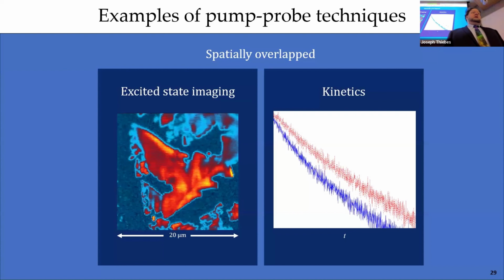And if you do it in spatially overlapped mode, as I mentioned, you can scan over the material. And this is a little microcrystal of perovskite, and it's showing it in its excited state. You can also just stay in one place and look at how the intensity of the signal decreases over time. How rapidly it decreases will tell you about how the recombination is happening, because as the population decays and relaxes, you'll get less and less intensity of signal.